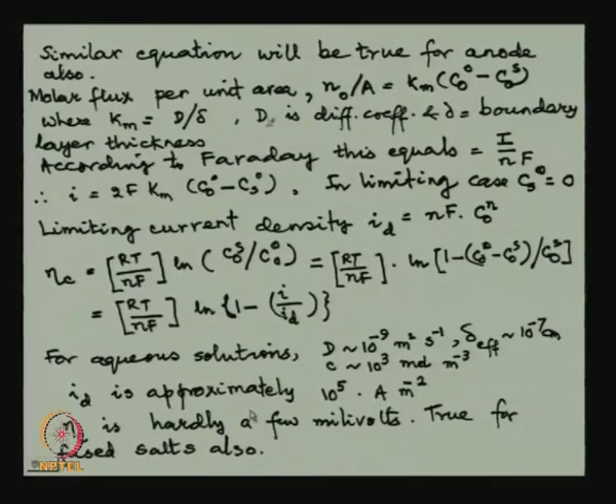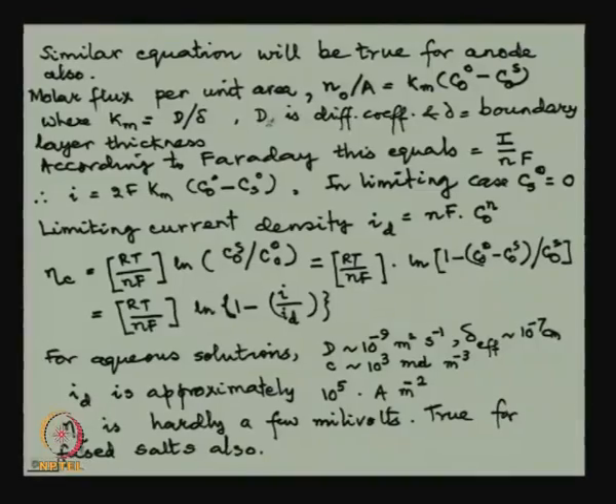moles per meter cube. So, the limiting current density approximately comes to this, that in many processes the limiting current density is 10 to the power 5 amperes per meter square. Per meter square you cannot pass more than 10 to the power 5. Now, this is very important. There is another thing, we can calculate the overpotential, but this comes out to be only a few millivolts. This is true for fused salts also. So, the phenomenon of overpotential does not change the voltage requirement much, which is a good thing.